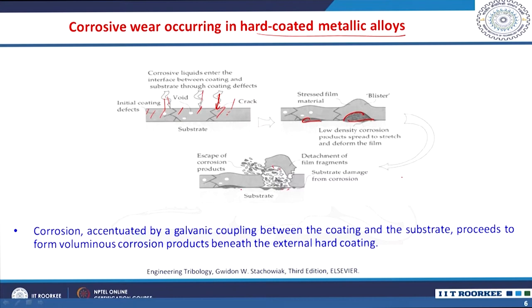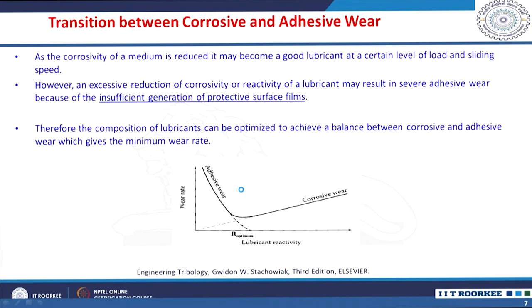So, you will have corrosion accentuated by galvanic coupling between the coating and the substrate, which proceeds to form voluminous corrosion products beneath the external hard coating. So, corrosive wear is one of the important wear mechanisms that occur in metallic alloys coated by hard materials in corrosive conditions. There always happens a transition between corrosive and adhesive wear.